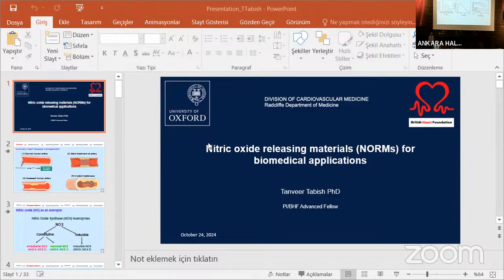This is another method called electron paramagnetic resonance, EPR, because there is a lot of controversy around nitric oxide detection, because the other techniques might be detecting nitrite or nitrate. That's why we use the spin trap method to trap nitric oxide using DETC-Fe, and the three-line graph clearly indicates that this is nitric oxide.